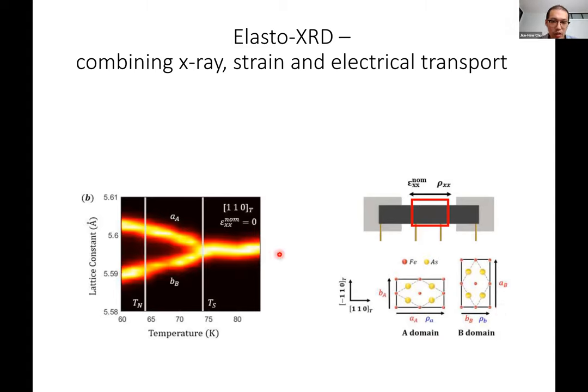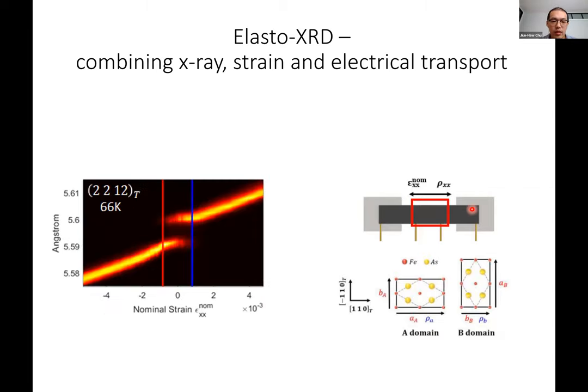So therefore, in the X-ray diffraction curve, you can actually see that one X-ray diffraction peak is split into two. This is because you see two lattice constants corresponding to two domains. Now, let's say we are sitting at this fixed temperature, and then we start to apply strain along the matched direction. Then what you can see is, as a function of strain, which is the x-axis, this is a nominal strain measured by the strain gauge, not the actual deformation of the samples.